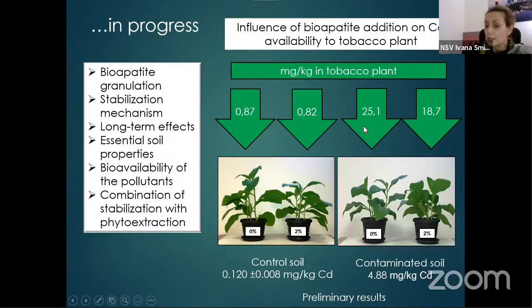What we concluded is that the concentration of cadmium in the tobacco plant is reduced after implementing the bioapatite to the soil, which means that the biochar effectively stabilizes the cadmium. However, this concentration is still very high, which means that the tobacco plant is a hyperaccumulating plant for cadmium, and such plants can be used to extract the residual mobile fraction of the heavy metals from the soil, in addition to heavy metal stabilization.